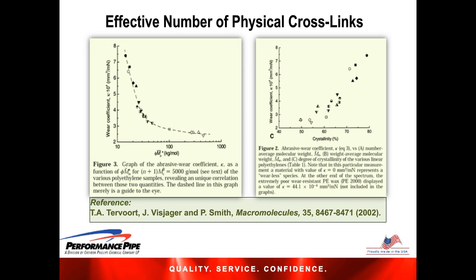On the right side, keep in mind again this was all data for polyethylenes only, and therefore more directly relevant. Crystallinity is directly tied to density, and you can see very clearly that as the density increases, the wear rate also increases in a fairly linear fashion, meaning once again that the lower density products would be expected to have better wear performance.